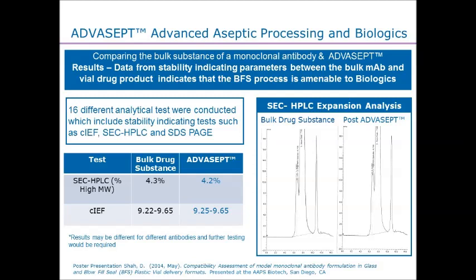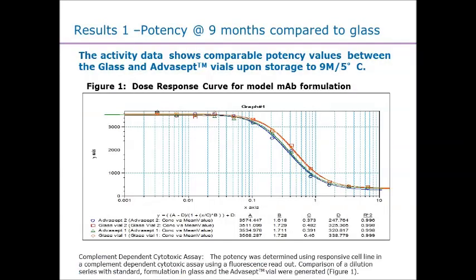We then took that to the next step. We filled the bulk substance into both ADVASEPT and glass vials, put both up on stability, and started running through results. One of the big things we added from the time zero test was activity — looking at potency, seeing what it looks like, marrying these two products and running the assay on both. What we've seen is that the performance of the molecule itself has really no difference between the ADVASEPT container and the glass container.